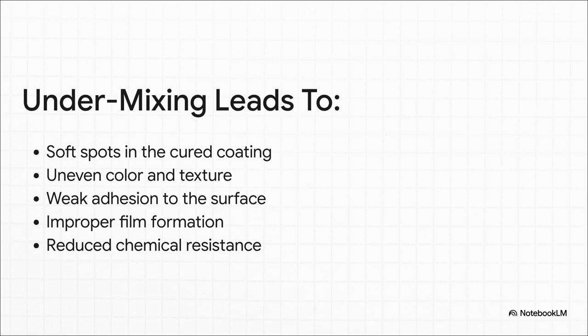In a batch that's been undermixed, the different components just aren't spread out evenly. Think about making a cake, but you've got pockets of dry flour in the batter. Those spots are never going to bake right. It's the same idea here. You get soft spots that never fully cure, a blotchy look, and this is the big one, weak adhesion. The coating can literally just peel right off.